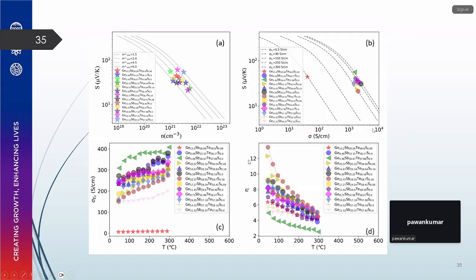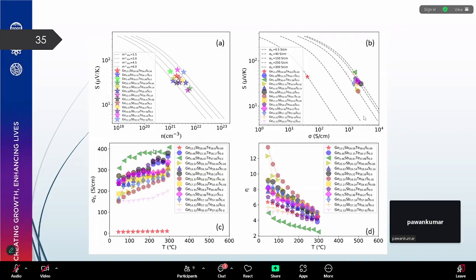We also checked the doping. It seems like it's still overdoped. It should be a negative value of beta, or higher doping, for the optimal doping. Similarly, are you grain size limited here? Or is the sigma-zero grain size limited here? It's supposed to be close to 4,000 in the bulk sample. I see. A few hundred, I think, at least a few thousand. But we have about a third to a quarter of that here. Okay.